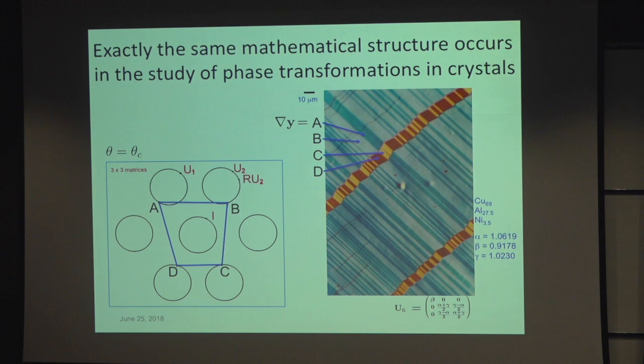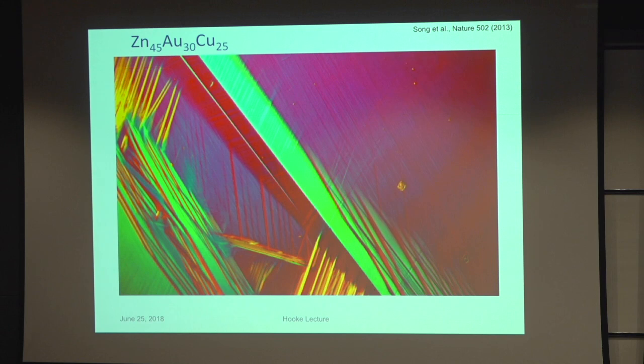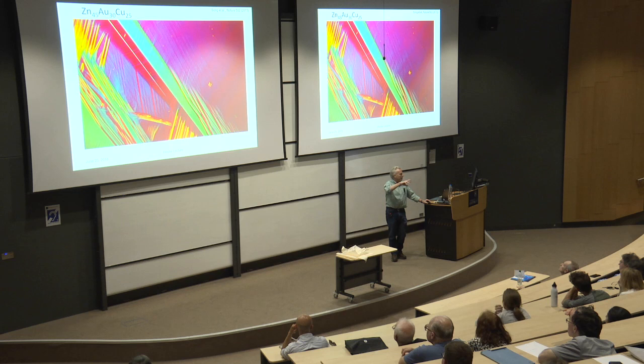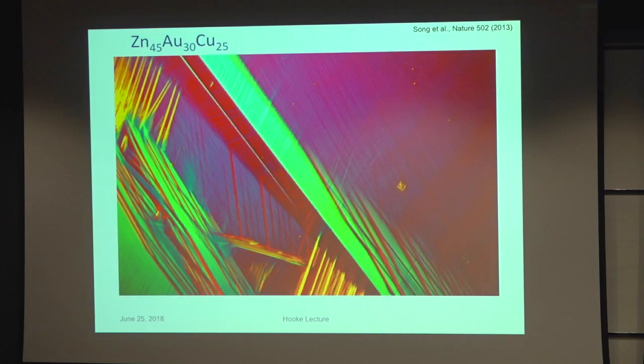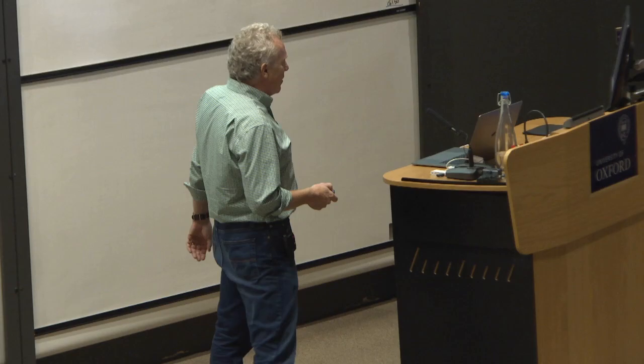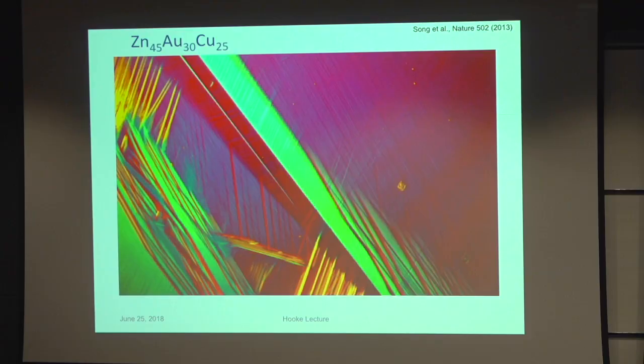And I want to show you a material that's been tuned. There are two sort of spectacular materials, and this is one of them, obtained by this kind of tuning of lattice parameters, so that there were many, many ways to fit together in completely non-generic conditions. It's fun to watch a movie of it transforming back and forth. By the way, I had six distortions in the case I mentioned before. This material has 12 distortions, but it's otherwise very similar to what I was saying before.